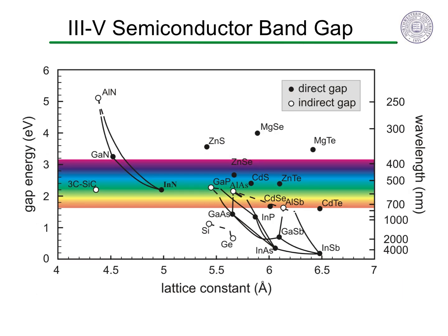For decades, the only LEDs that you could find easily were red LEDs. That is because III-V semiconductors that we could easily make then, such as gallium arsenide based, could be alloyed with elements such as aluminum and phosphorus, which increase the band gap into the red region. The smaller phosphorus and aluminum reduce the lattice constant, increase the bonding strength, and open up the band gap a little. Silicon and germanium have band gaps too small and are also an indirect gap, which is not good for